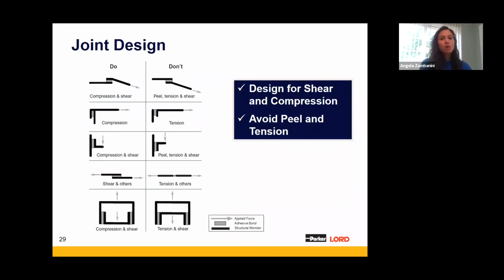Now, the last thing that we'll go over is just some joint design. When using adhesives, you really want to make sure that you're trying to design for as much surface area as you can. The greater the surface area, the stronger the bond is going to be. We like to aim for at least a 1/8 inch bead, which squishes down to about a 3/4 inch to 1 inch overlap. And that'll really ensure that you have a lot of good strength in there. And you also want to make sure that you design for shear and compression and try and avoid peel when possible.